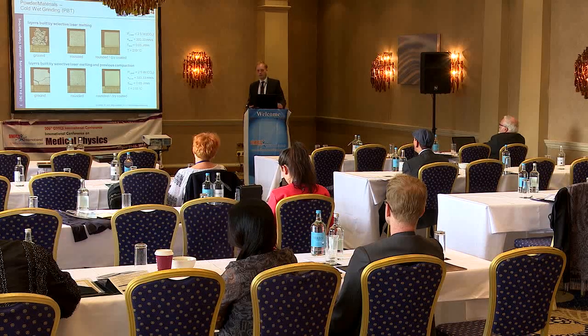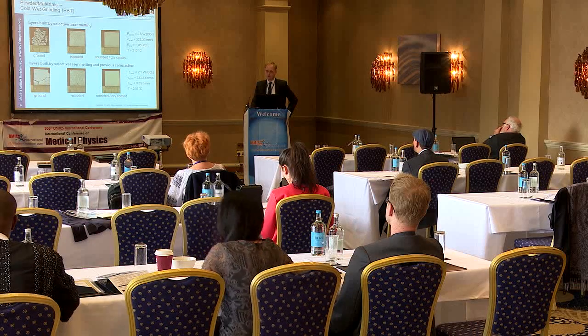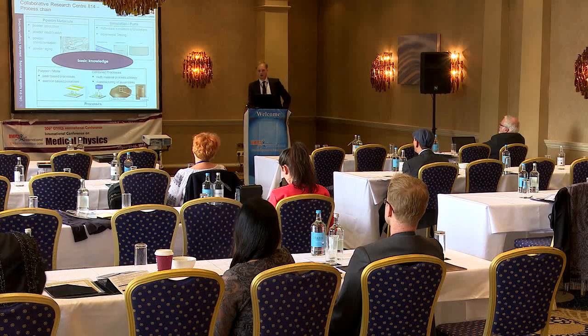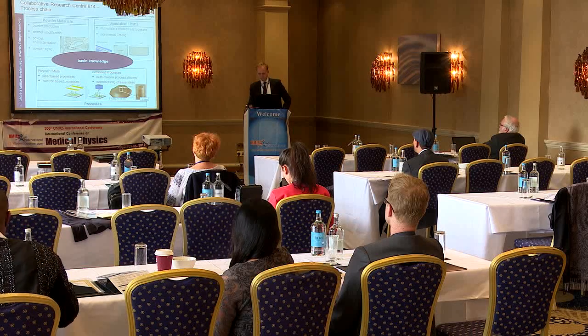But with the rounded powder, you get a much better packing density, even a denser molten layer. And if you functionalize the rounded powder, you even can get a very dense layer, the highest density within this experiment. Another way is to functionalize the powder as well as a previous compaction of the powder. With this technique, you can get very dense layers with nearly no porosity. So this was an example of how the process interacts with the material.